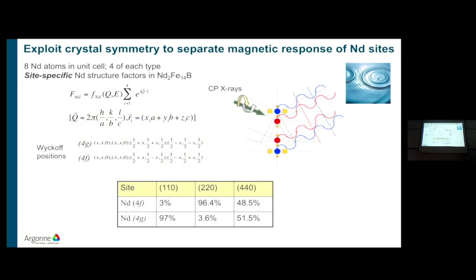So we go back to the very simple structure factor where the atoms are in a particular arrangement, in the symmetry of the lattice, and they have different structure factors. So when you look at the contributions at a particular Bragg condition from the one type of neodymium or the other, in this case the 110, 220, 440 Bragg peaks. It turns out that at the 110, mostly one neodymium site, the G site, contributes. If you go to a 220 Bragg peak, the structure factor, or the interference between the 4 neodymium atoms, there are 4 of each, they interfere when they scatter. Now at 2, 2, 0, the F sites are dominant, and at 4, 4, 0, they are equal.